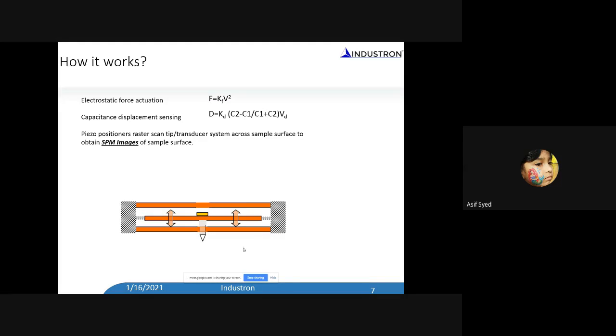To measure the displacement, we measure the capacitance between these parallel plates. You know that when you have a parallel plate with an air gap, there is a capacitance. So when the center plate moves in between these two outer plates, the gap is changing. Because the gap is changing, the capacitance is going to change. And if you have a way of measuring the change in capacitance, you can measure the displacement. So with this simple concept, we can apply force and measure displacement. So this is what we use. It's a very simple concept,